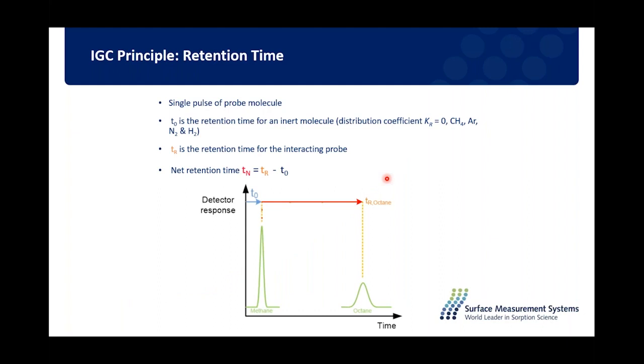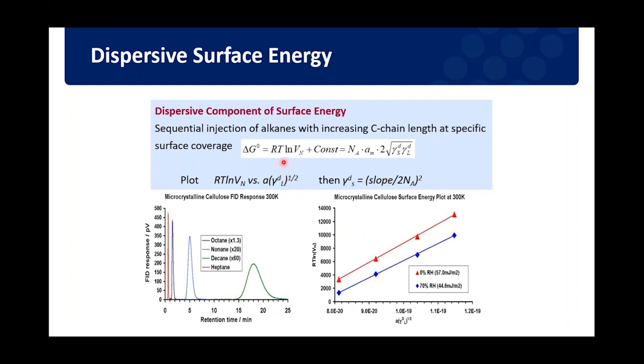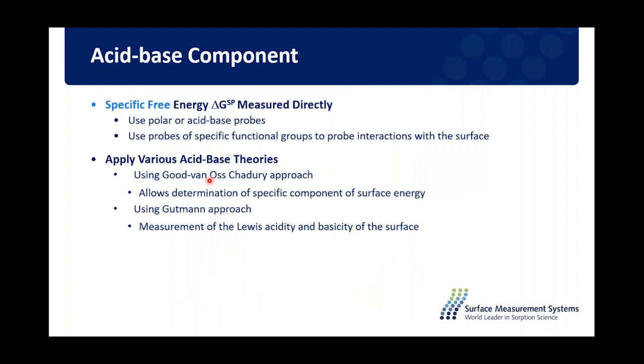You inject different probe molecules, measure the retention time, which gives the retention volume related to the free energy, and that gives access to the surface energy. To get the dispersive component, you inject a few nonpolar probe molecules — typically a series of straight-chain alkanes — to get gamma D, the dispersive component of surface energy. To get the Lewis acid-base contribution, you inject some Lewis acid-base probe molecules. Together, a few nonpolar and a few Lewis acid-base probe molecules give the total surface energy of the material.